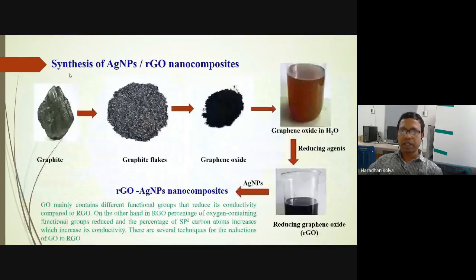And I want to focus on this material that I have synthesized, that is silver nanoparticles with reduced graphene oxide, RGO, a nanocomposite material. Graphite is collected from the mineral ore, and it is ground into graphite flakes. Using the modified Hummers' method, you can synthesize the graphene oxide. After the synthesis of graphene oxide, you disperse it in water and add some reducing agent, and you will get this reduced graphene oxide. After this step, I just mix the silver nanoparticles in here, and I get this silver nanoparticles with RGO nanocomposite.